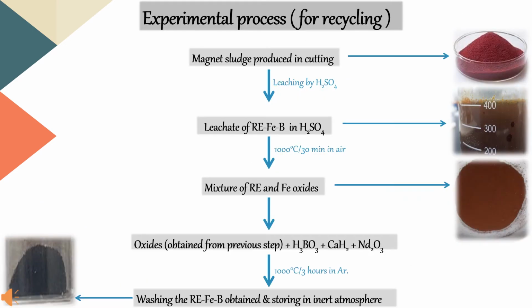Here is the experimental process for the recycling of the ReNdFeB magnet sludge. The first step was obtaining the sludge. This sludge is produced during the cutting of the NdFeB magnets, and the sludge obtained was leached by sulfuric acid, and the leachate is actually the sulfates of the Re and the Fe.